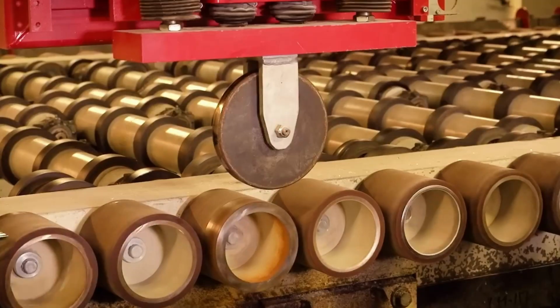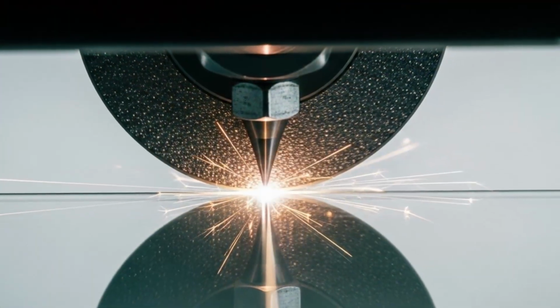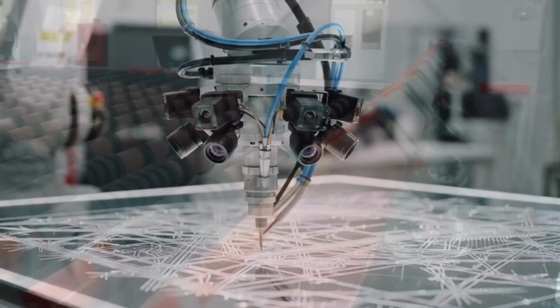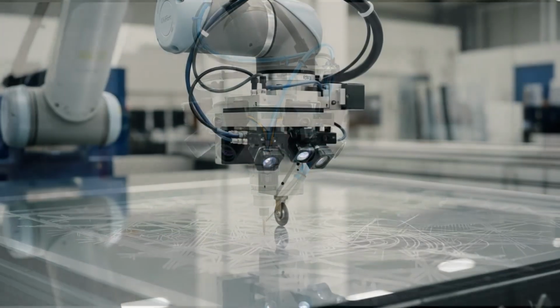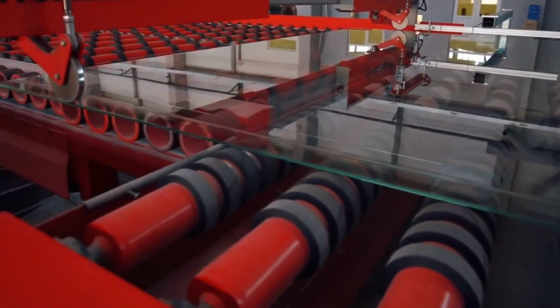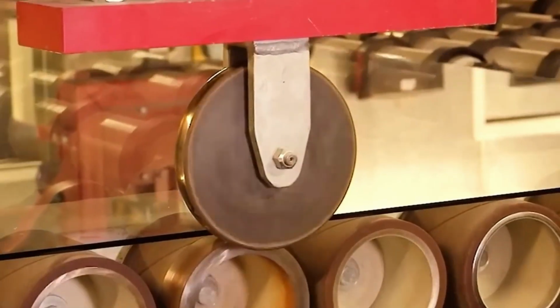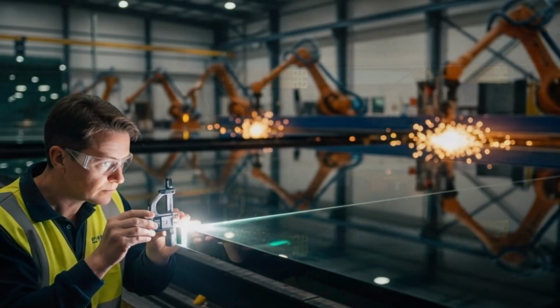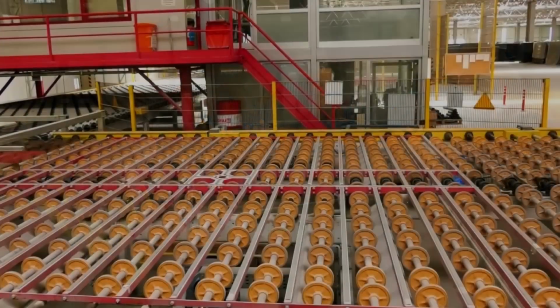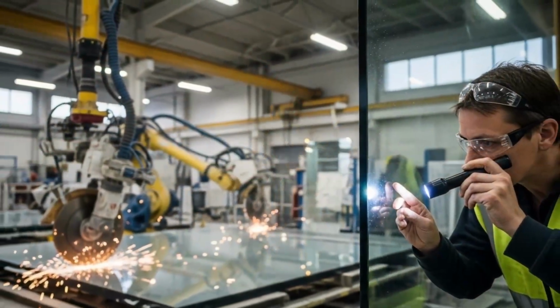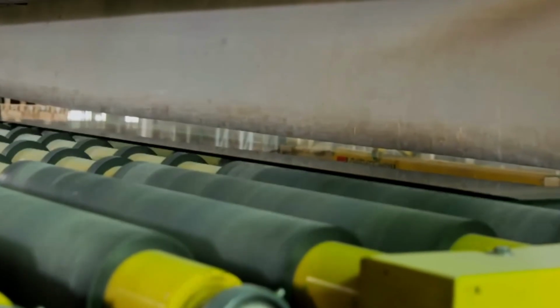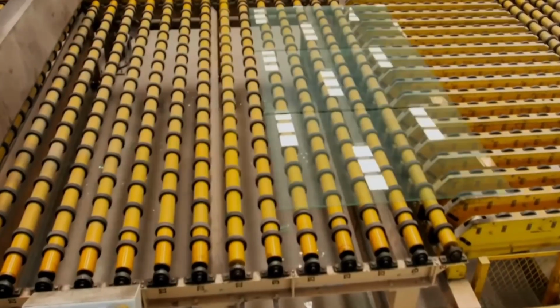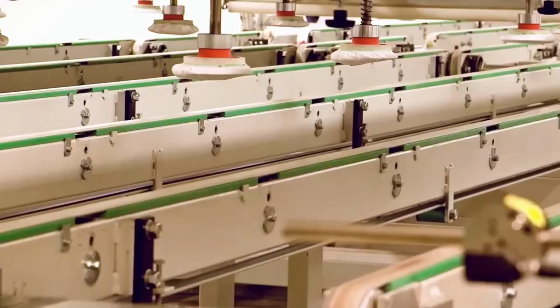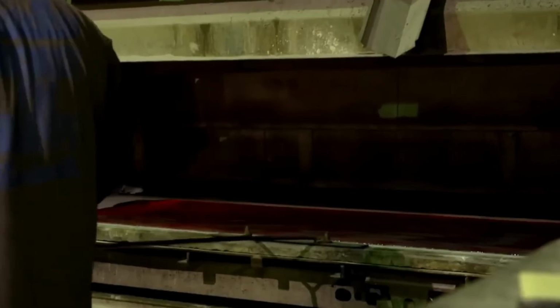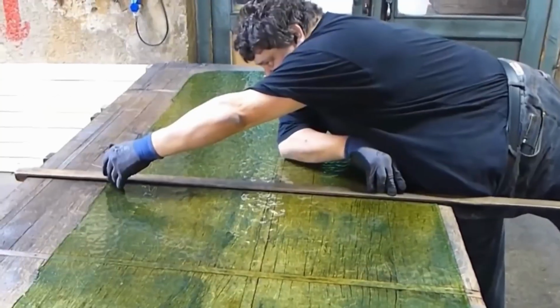Precision cutting is a key step. Diamond-coated wheels or lasers score the glass without creating splinters or microcracks. Robotic arms with machine vision guide the tools to the exact dimensions required by the customer. From 2 by 3 meter window panels to much larger formats for architecture. Once cut, the edges are too sharp to handle safely, so they move to progressive polishing machines. These use abrasive wheels, from coarse to ultra-fine, to remove sharpness and leave smooth, safe edges. To prevent heat from damaging the glass, the process is constantly cooled with recirculated water, which also saves resources.